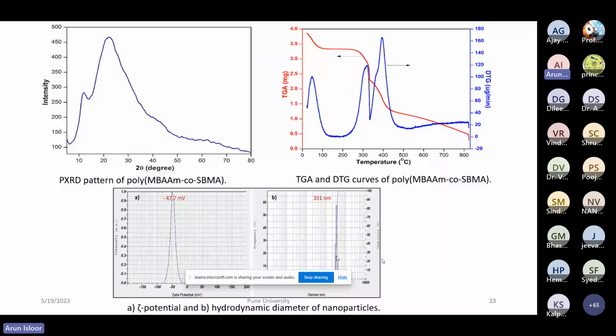And the particle sizing through the particle sizing analyzer instrument showed approximately 331 nanometer, whereas in the FESEM it showed less than 50 nanometer. You may ask the question here. The reason is, when this is suspended in distilled water or deionized water, the particles develop hydrodynamic bondings or attraction, so the particle size appears larger in this particular analysis. Hence the size is always larger.